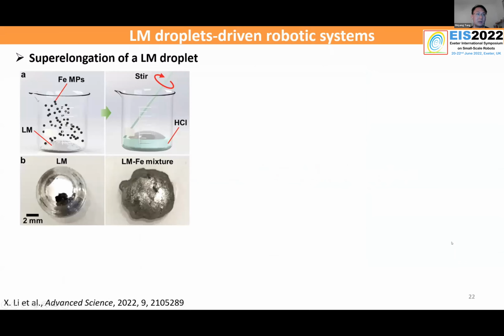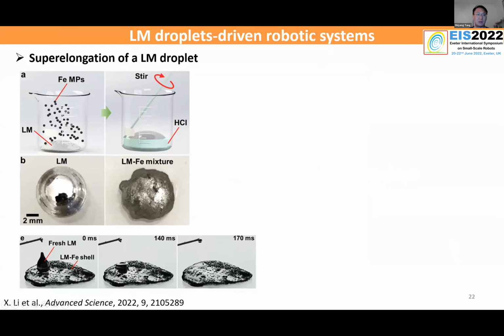And finally, I'll just quickly talk about recent work. Instead of controlling the locomotion of the droplets, we are also able to control the morphology of liquid metals. In this case, we mix liquid metal with some iron microparticles to create a liquid metal iron particle shell on the surface, and the shell is able to engulf pure liquid metals.